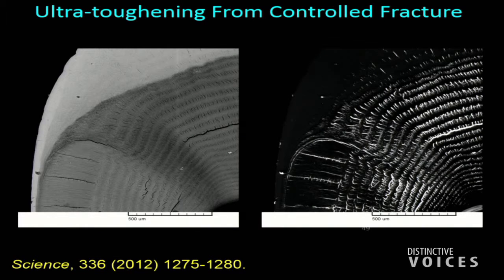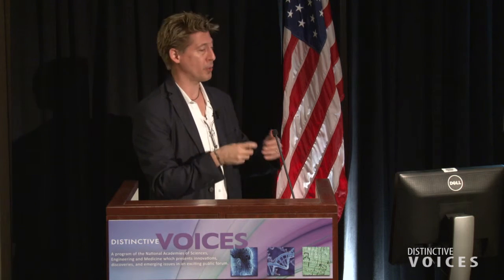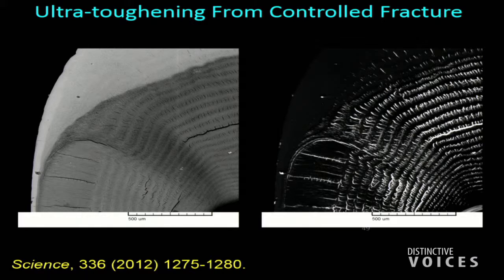So what we found was the club, after about 10,000 impacts, I didn't have a grad student counting the impacts, of course, but we estimated it based on the fact that a mantis every 3 to 6 months will molt, it will shed its club and form a new one. Based on its feeding habits, and knowing that between molts it can impact from 10 to 50,000 times, this was somewhere 10 to 20,000 impacts. So this is a section of the club. We cut it in half, and this is a backscatter image where you see the brighter mineral. This is the periodic region.